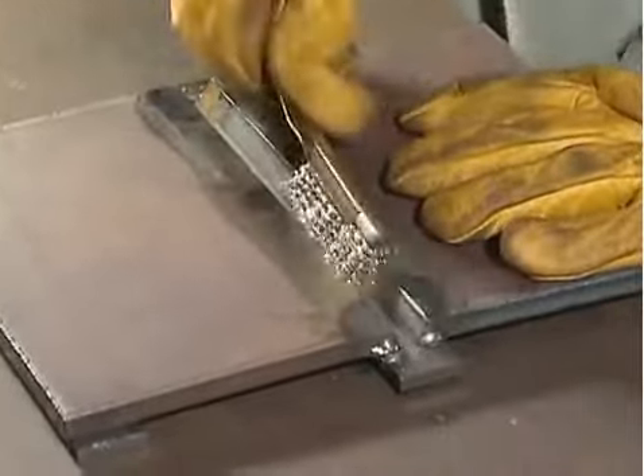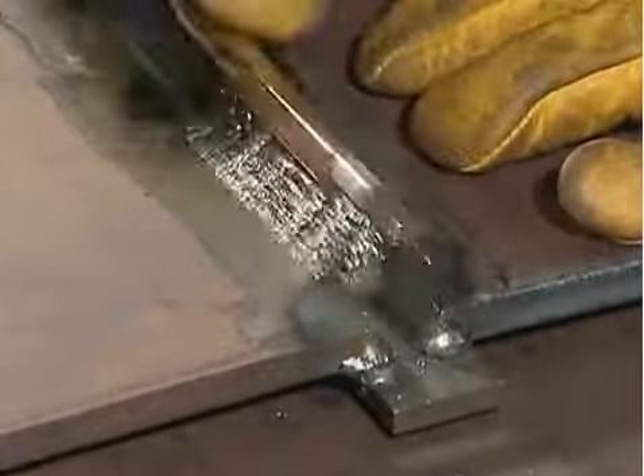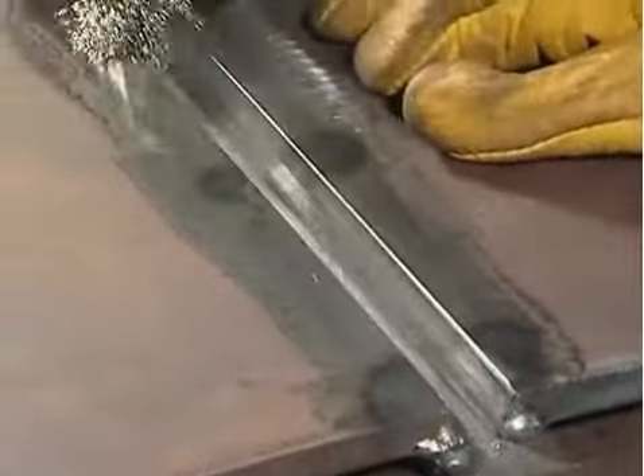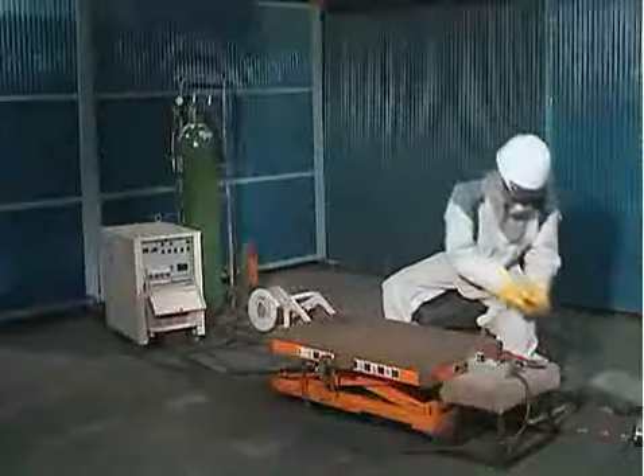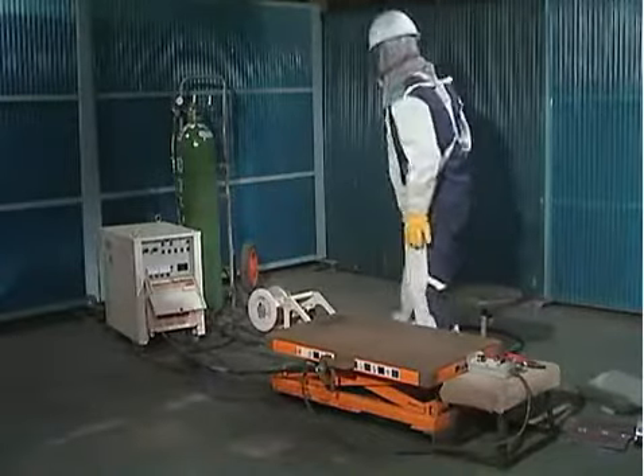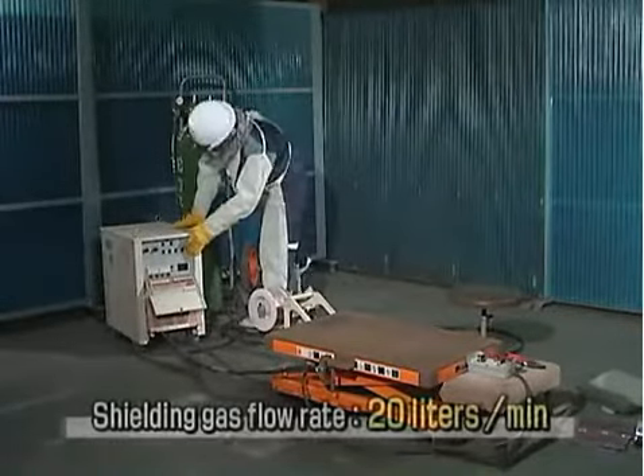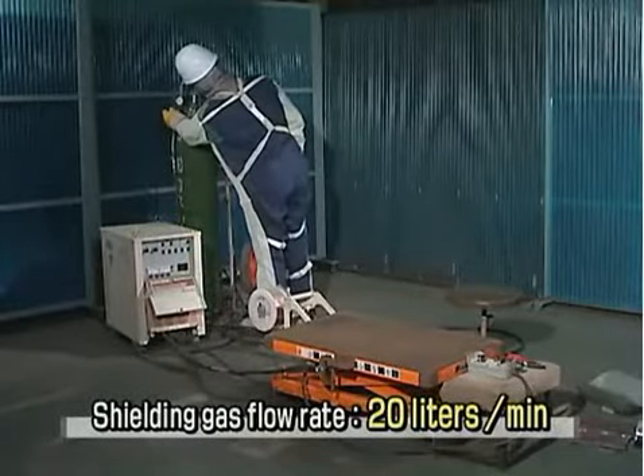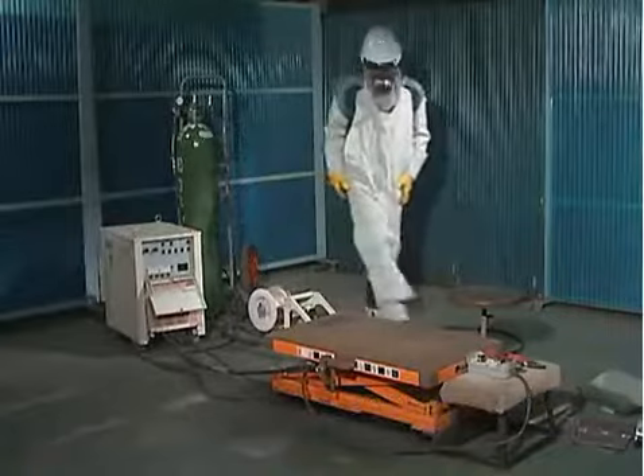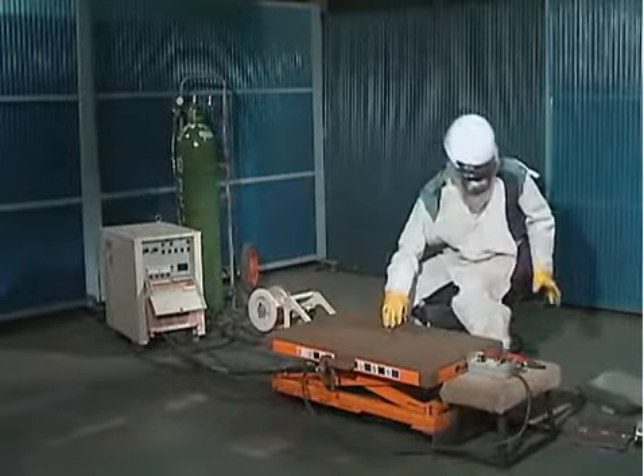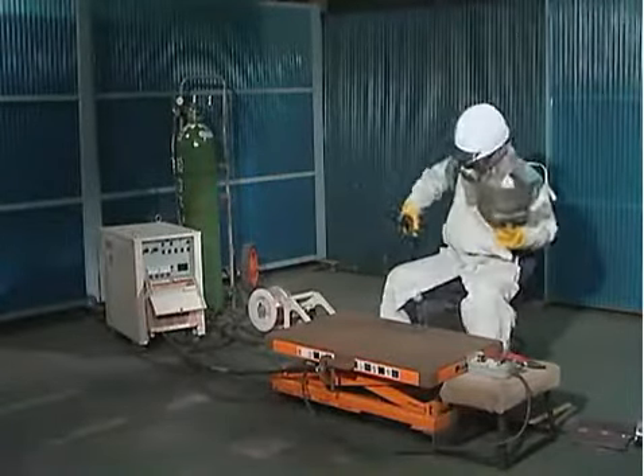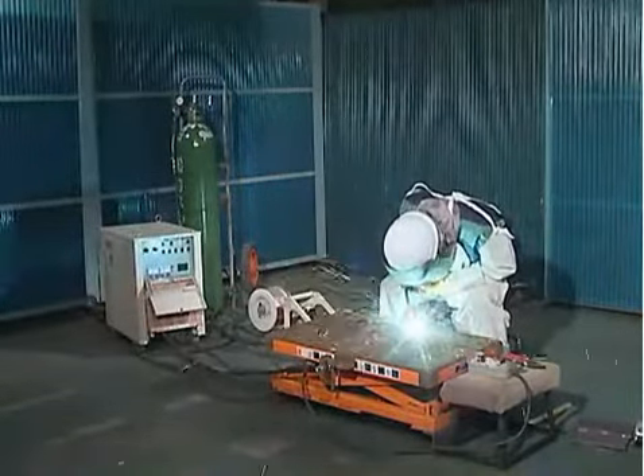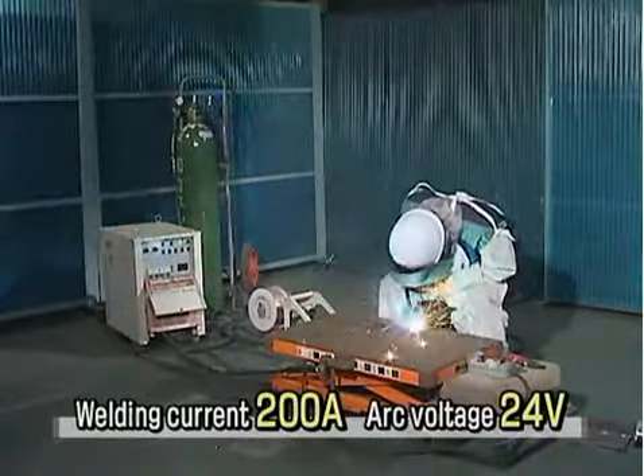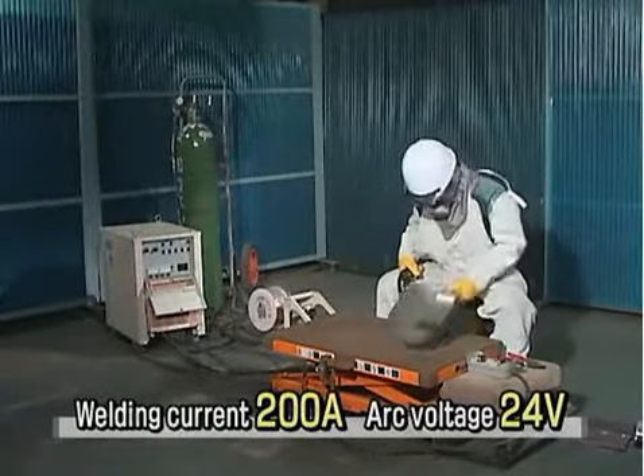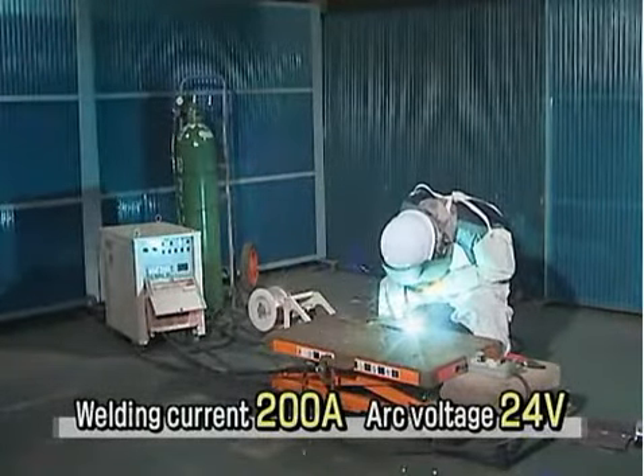To prevent weld defects, make sure that no oil, paint, moisture or other foreign matter adheres to the surface of either the workpiece face or the groove face after the tack welding, and also watch out for rust formation. Next, check the shielding gas flow rate. Combined with a proper wire extension, set the welding current at 200 amperes and the arc voltage to 24 volts. To set the voltage, don't simply set the meter, but check the arc and adjust the voltage so that the arc length is just right.